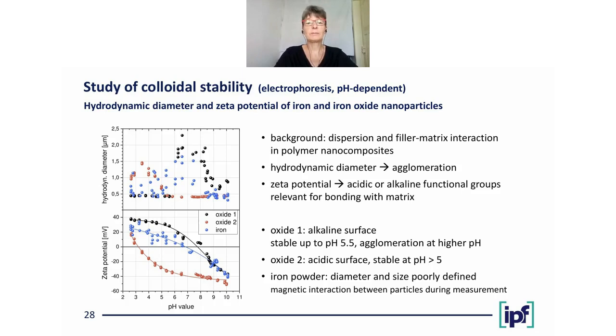And you can see here very nicely for the oxide shown by the red dots, we have a low zeta potential at low pH values and an increasing negative zeta potential if the pH value increases. That's why these particles are well dispersed above pH 5, and they agglomerate at lower pH values when the zeta potential is low. For the particles shown by the black spots, it's quite opposite. They are well dispersed at low pH values and agglomerate at high pH values. So for practical applications, we have to select the appropriate pH range for our application.